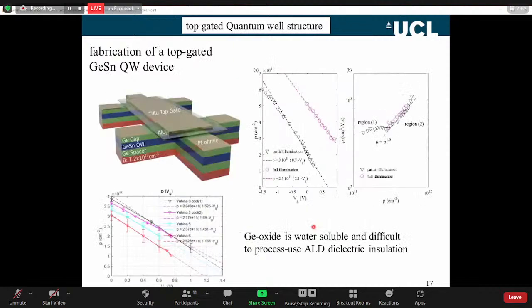So we had to make an FET device. The FET device, field effect transistor device, consists of a Hall bar, a standard Hall bar where we've etched away. We use standard chemical etching to make the pattern. We put down an ohmic contact, which is made of platinum. So this is the source, this is the drain. These are the potential arms where we can measure resistivity along the bar. We can also measure the Hall voltage across the bar.